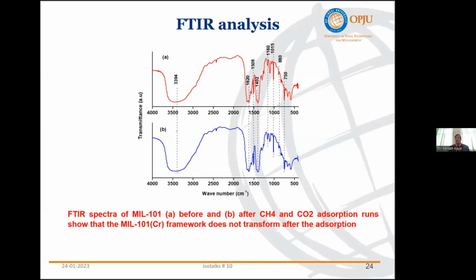Then the deformation vibration of the carbon-hydrogen bond, the CH bond, at 1160, then 1015, then 880 and 750. So all these peaks you can see before and after, all the peaks remain intact.